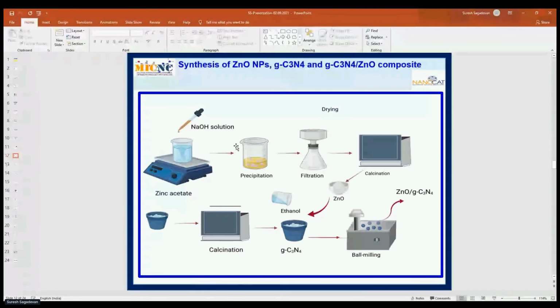And then we go for centrifugation to obtain the product. The product was dried in an oven at 100 degrees Celsius to remove the moisture. Finally, it was ground to a fine powder, and then we calcinated it at 400 degrees Celsius. We obtain this zinc oxide nanoparticle, and then we prepare the bulk graphitic carbon nitride.